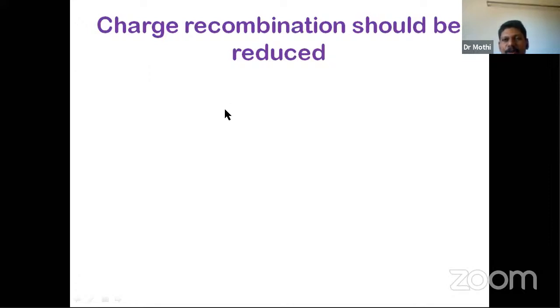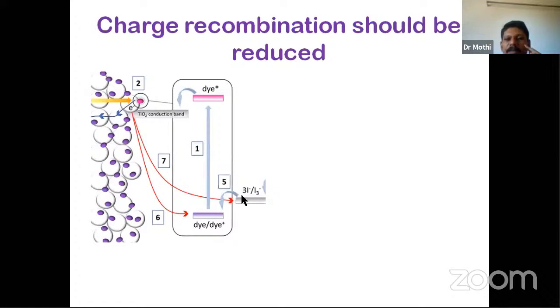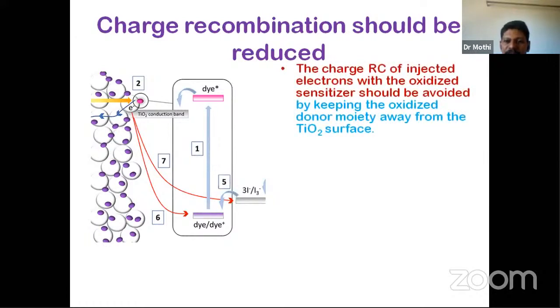I have already shown two red lines, right? So I'm showing it again. These two red lines are unfavorable or reverse processes which are not desired. Why are they not desired? Because they quench the dye, they quench the electrolyte, and they reduce the final power output. So this charge recombination should be reduced. How can we reduce it? We can keep the oxidized dye away from the TiO2 surface. When light shines upon the dye, it becomes oxidized or excited. Once it is close to TiO2, the TiO2 can give the electron back to the oxidized dye.